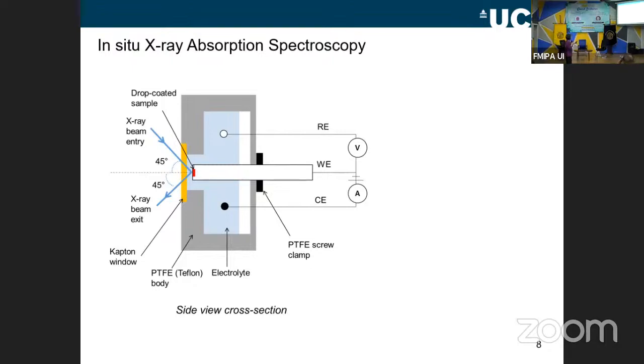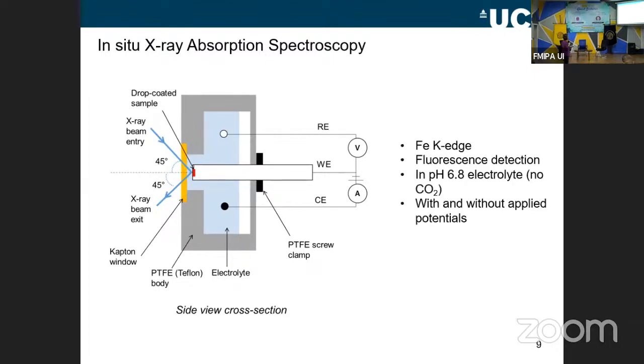What I have here is a cross-section through the side of my electrochemical cell. I have my working electrode, my main electrode that I'm applying the potential to, and I've put my sample right on the surface of the electrode. So that's where my greigite is. Then my X-ray comes in through a window onto my sample, and I measure the X-ray that comes out. So it will tell me what's been absorbed. And then I have my 2 other electrodes in the solution, and I have my electrolytes in the solution as well.